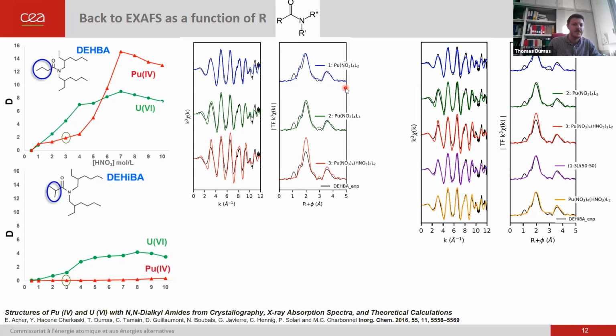Now I'm coming back to this difference between the 2 monoamide structure, and I compare again to our DFT model spectra. So as I said, the tetranitrate inner sphere complex works pretty well for this one. So this we knew already from the fit, but it confirms that the DFT approach to model an EXAFS spectra in this case works pretty well. And if you try other structures, it works much less.